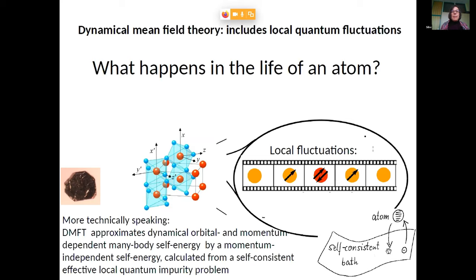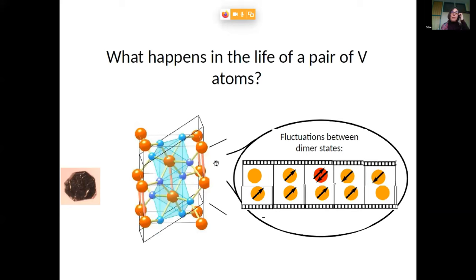Namely, I have talked before about a vanadium dimerization. And now I'm speaking of the happenings on a single atomic site. And that is clearly inconsistent. So what we actually have to do, and what we did, is rather indeed think of a pair of vanadium sites. So what is actually taking the role of the effective atom of usual DMFT here is an effective dimer problem. So we think what can happen on a pair of vanadium atoms and let that fluctuate in time.